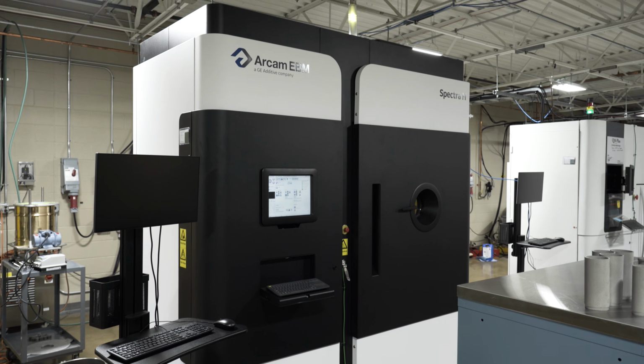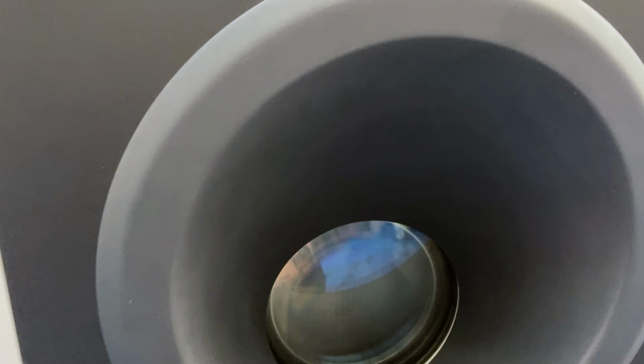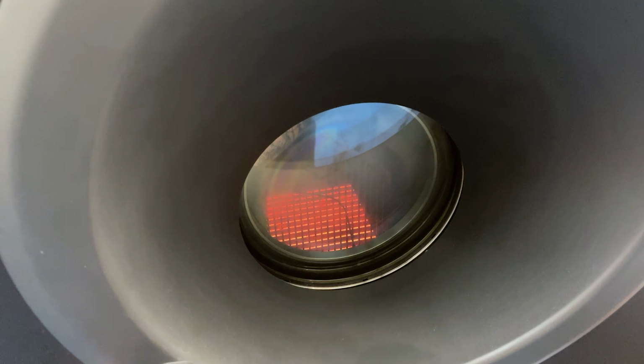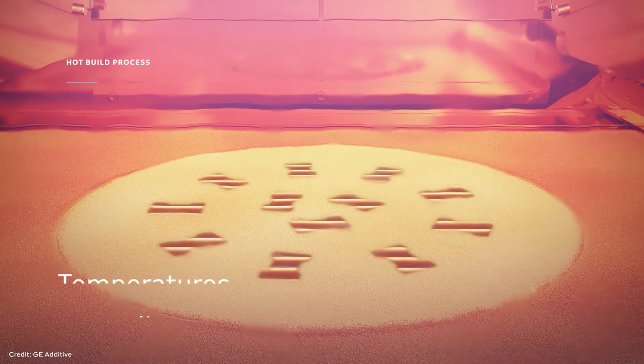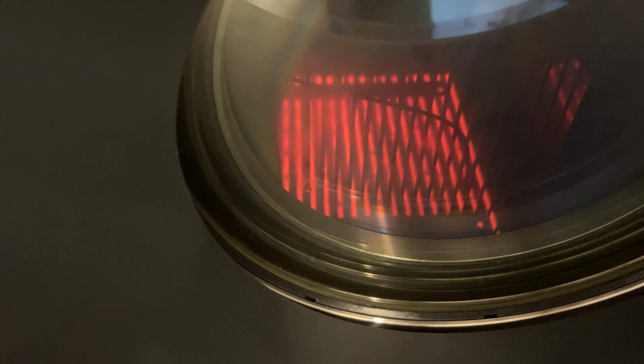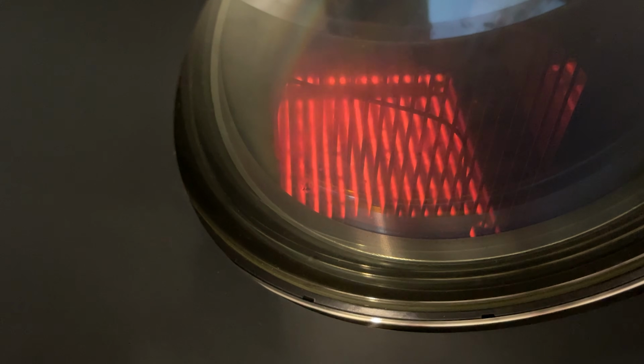Specifically for tungsten, we chose this for three factors. One, the vacuum environment limits interstitial, i.e. oxygen, contamination pickup, which is very detrimental to tungsten and refractory alloys. Also, there's the ability to preheat the powder bed to high temperatures, which you cannot achieve within the laser powder beds today. So we're looking at temperatures in excess of 1400 Celsius in the melt area, which aids us in maintaining thermal gradients, especially when we're trying to stay above the ductile to brittle transition of tungsten.